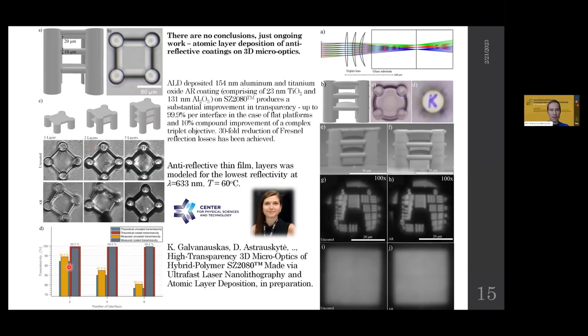As we see, the non-coated transparency is reduced from 95 to 88 to 80%. So every next layer significantly reduces the passing light. Whereas when applying the coating, it seems it's not dropping at all, or measured from the reflections in contrast, it seems like it's improving, but this is due to the performed calculation.